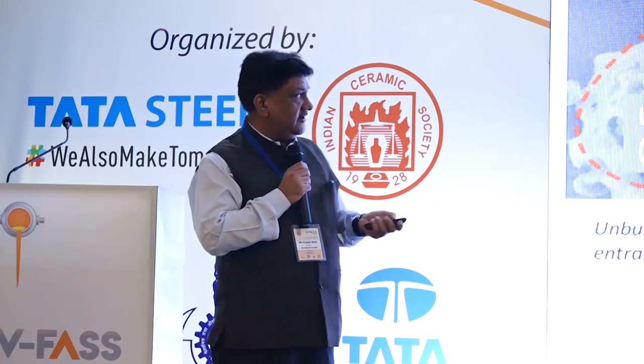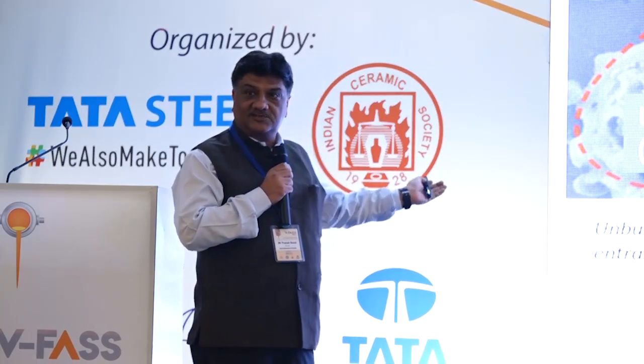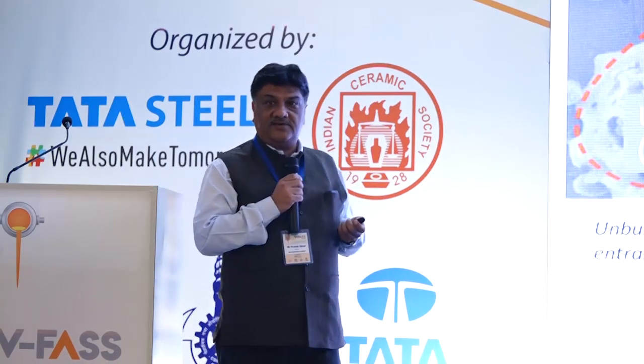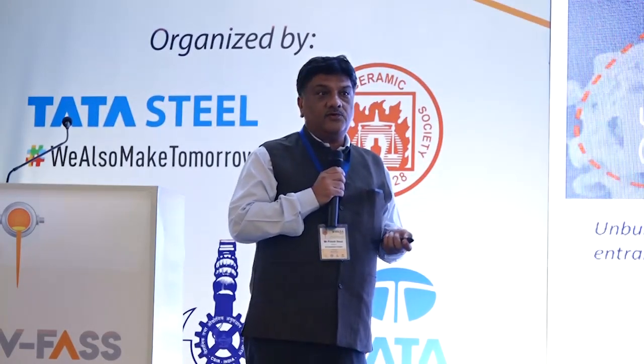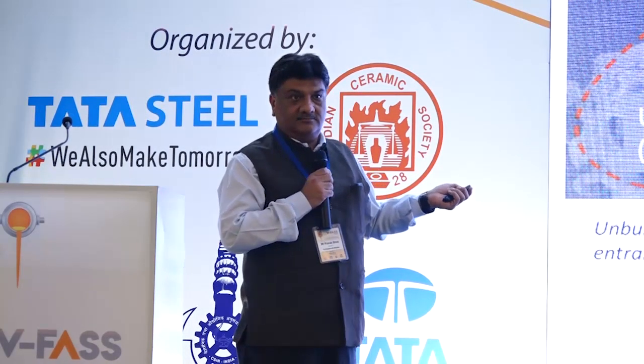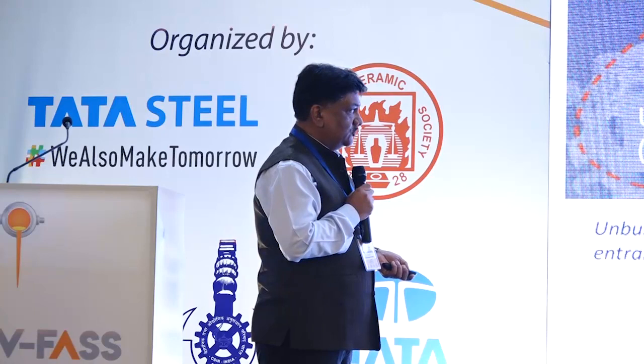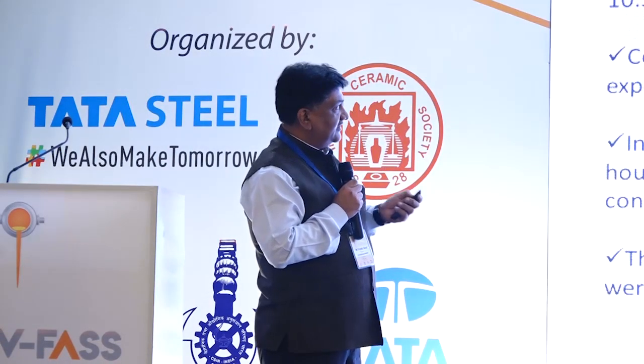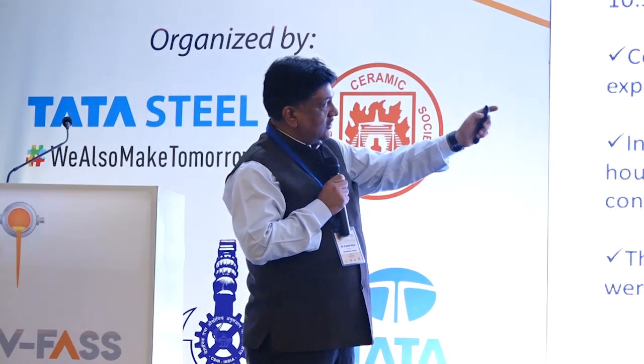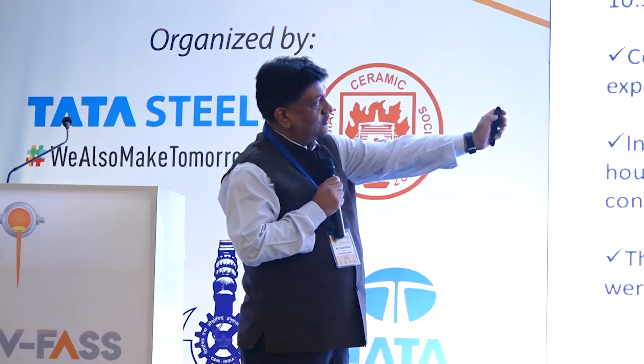We developed jointly a carbon blocker, which is basically a surfactant element, which improves the workability, because workability was a major challenge. So that basically improves the air entraining behavior, and this is making it workable. And we have consumed, as of now, around 3,000 tons of this pond ash and coarse fly ash at Gujarat and various other plants across the country, where we made this usable with a better dispersibility. These are the results. Some of the results in the concrete while using high LOI or coarse fly ash, where you can see the first column in the table, after parameter, is without carbon blocker agent, and the second one is with carbon blocker agent.